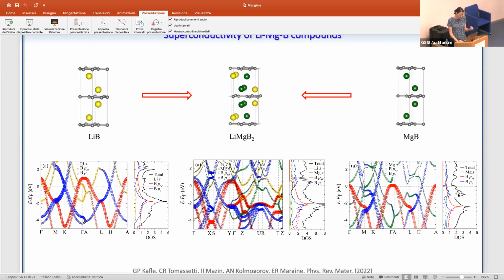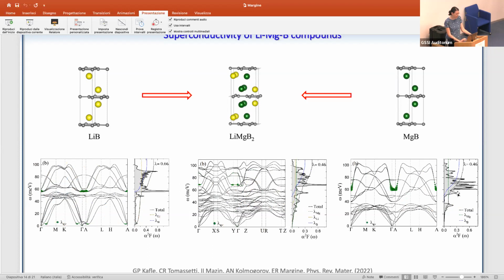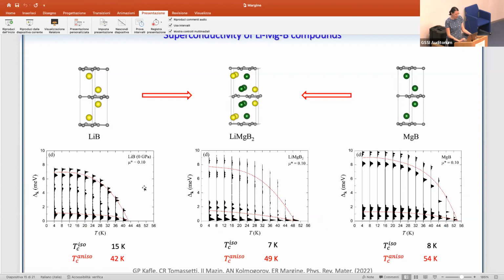So now, what happened when we look at the coupling? In the case of both lithium MgB2 and magnesium boride, we found much lower coupling than in lithium boron. In fact, we found a value of 0.46. And this is due to the lack of coupling from the low frequency modes in lithium boron. Indeed, if we exclude these modes when we estimate lambda, we basically find a similar value of 0.46. So we found that this mode has quite a significant contribution to the total lambda.